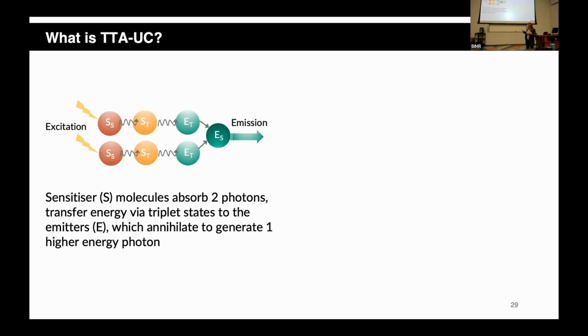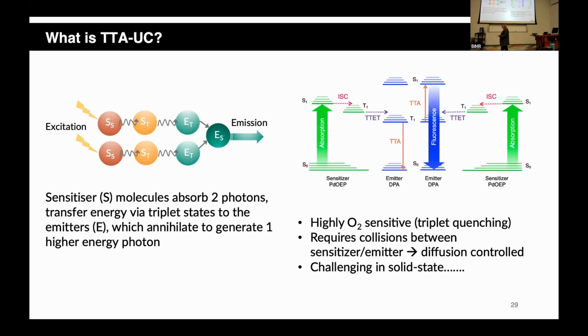It's perhaps easy to look at the Jablonski diagram to understand this. So what does this look like? So here's our sensitizers, they absorb the light, we get energy relaxation via intersystem crossing to the triplet state. Then we get triplet energy transfer to the triplet state of our emitter on both sides. And then these two triplets annihilate, one relaxes to the ground state and one goes up to the higher energy singlet state, and this then relaxes, giving out light.